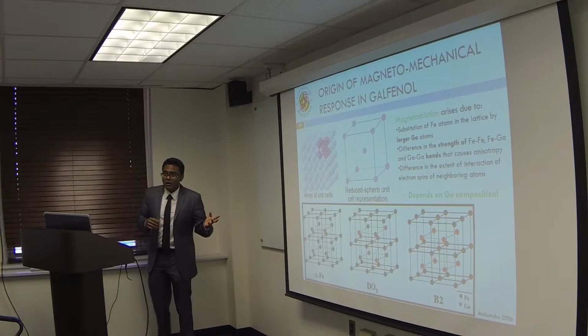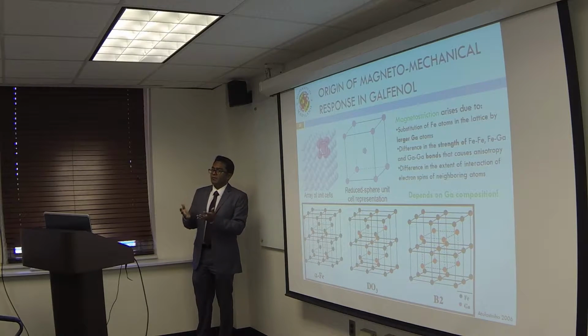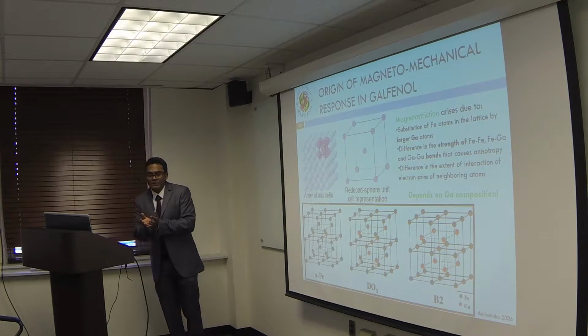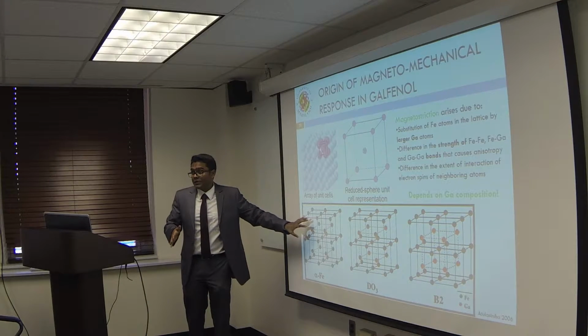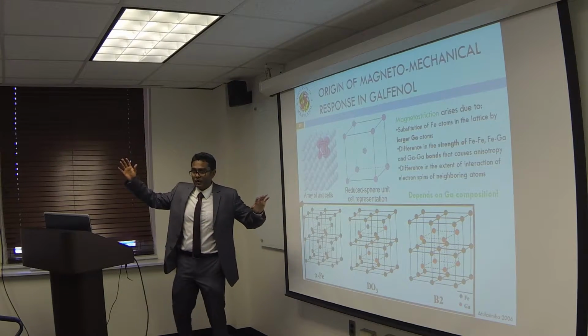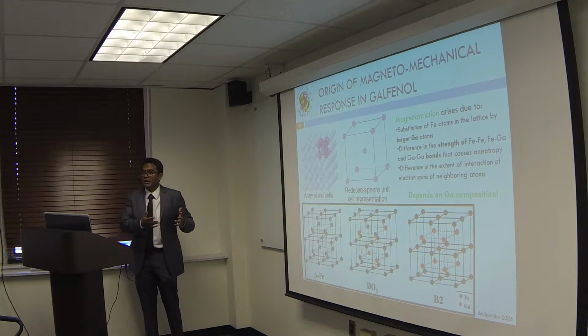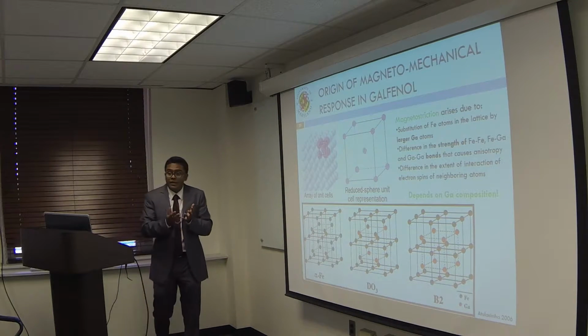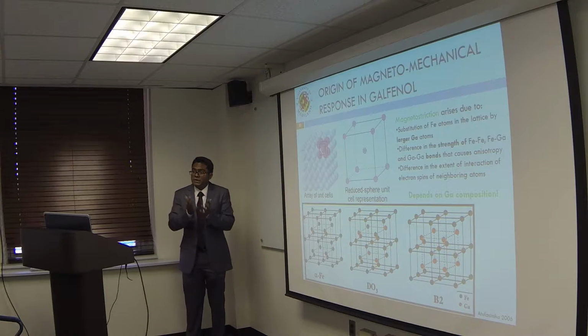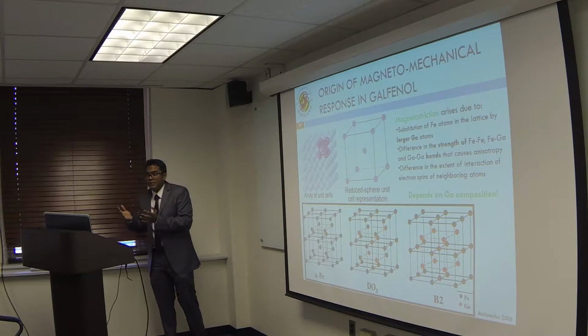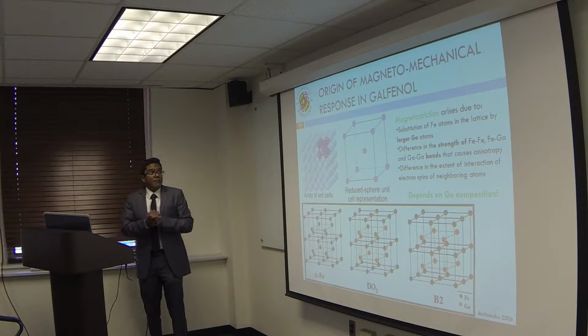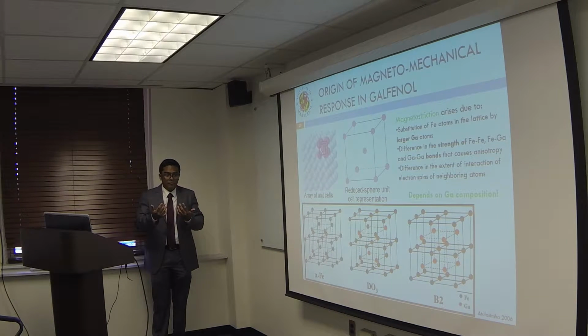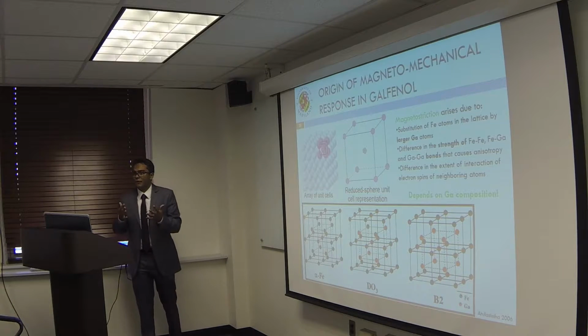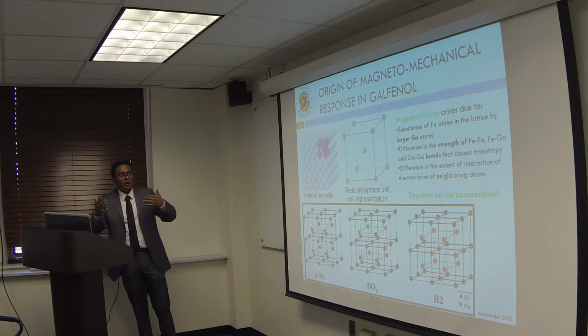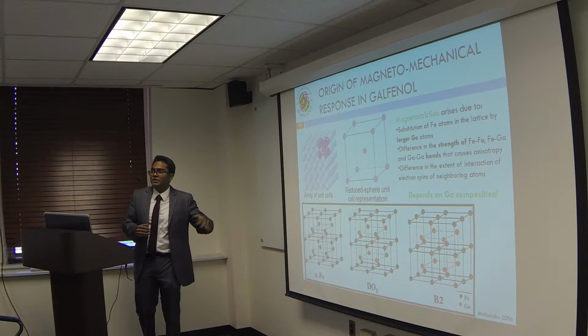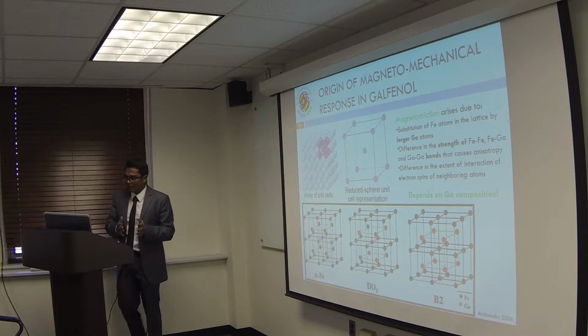So in Galfenol, there is an additional anisotropy effect because of the addition of gallium atoms. Iron itself is magnetostrictive, but the value rises up by orders of magnitude when you start adding gallium atoms in there. And the reason for that is the gallium atoms are larger than the iron atoms, and the strength of the iron-iron bonds and the iron-gallium bonds and the gallium-gallium bonds are different. And because of this, there is an additional anisotropy that is being introduced to the system, and this leads to a larger magnetostriction. And this magnetostriction is very dependent on the composition of Galfenol.